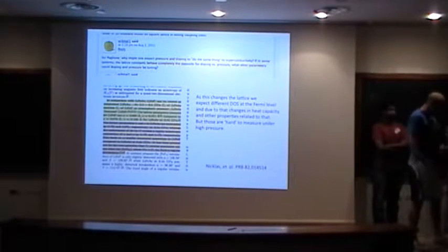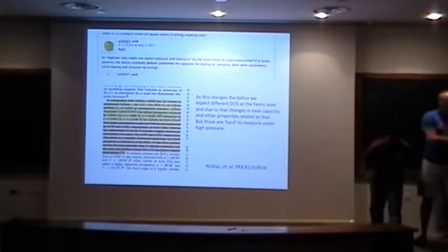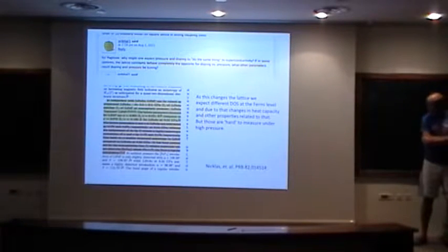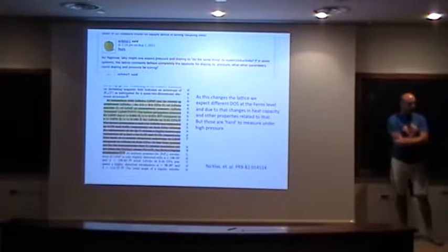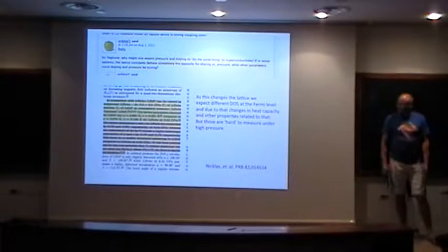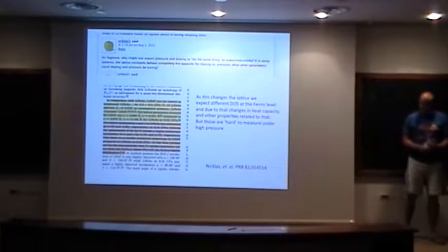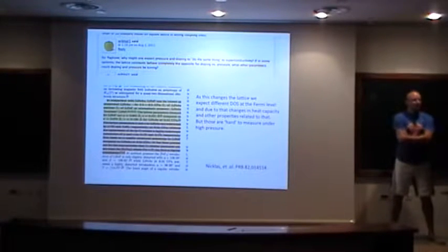Okay, I'm going to try to first go on one of the questions, which is, why might one expect pressure and doping to do the same thing to superconductivity if in some systems the lattice constants behave completely the opposite for doping versus pressure? What other parameters could doping and pressure be tuning? Okay, so first of all, we had the example on the barium 122, barium iron arsenide. We apply pressure, and we see superconductivity appears. So to sort of answer that question, I wanted to come up with another example that actually to me is a bit more familiar, which is the 111 compound, lithium iron arsenide, which seems to behave the same way.